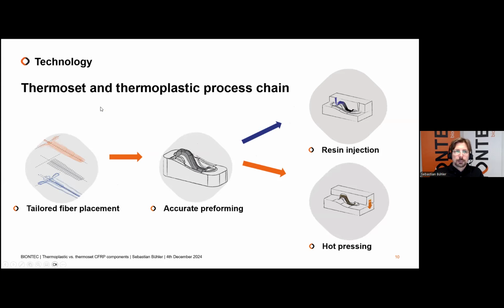It's the classic thermoset route. We use any kind of dry fibers, from the roving or the yarn, and then we stitch the layers on top of each other, and in every layer we can achieve the perfect orientation of the fibers. Then with fewer preforms and the net-shaped geometry, we can go into an accurate preforming. This depends on the part. For the brake lever here, for example, it's quite easy because it's only one layup. And with this dry preform, this 3D preform, we then go into the RTM mold and inject the resin.